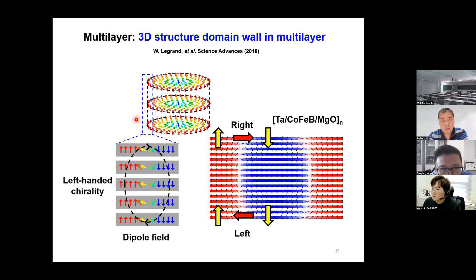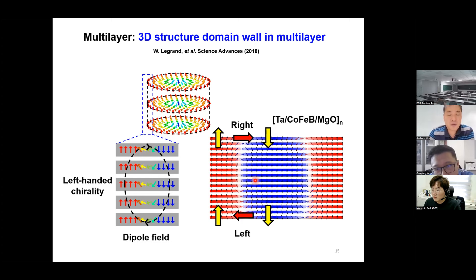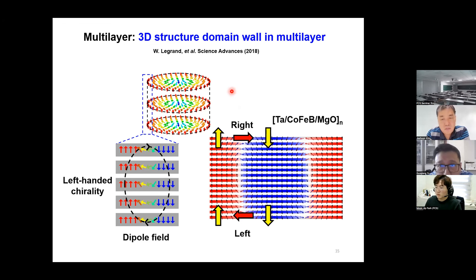It is actually straightforward to analyze. Assuming we have a multilayer with domain magnetization pointing up on the left and down on the right, we can draw the magnetic flux based on this spin texture. In the domain wall at the bottom, the spin follows the magnetic flux — that's fine. However, on the top, the magnetization in the domain wall is against this flux. If the stray flux is strong and DMI interaction is not strong enough, the spin here will be reversed. This is exactly what we see in simulation using the parameters of our materials — we get this complicated spin texture in the multilayer, similar to previous published work.